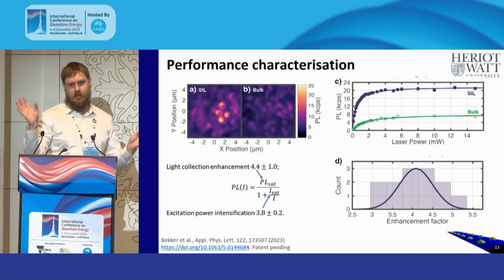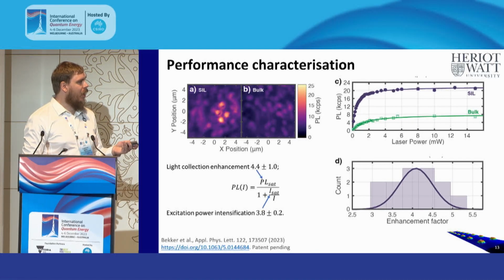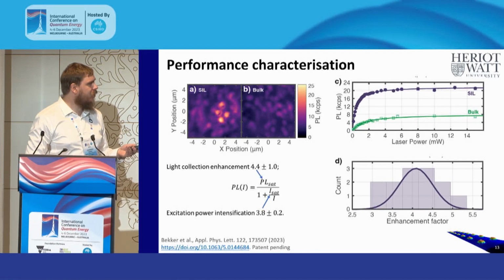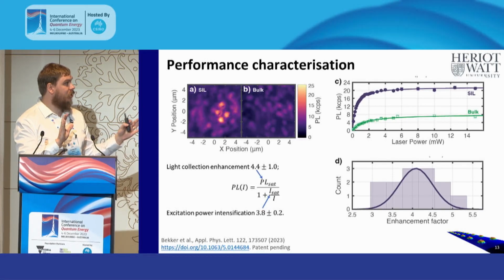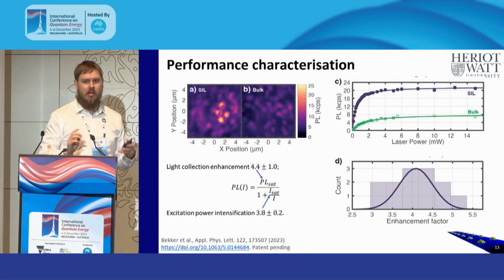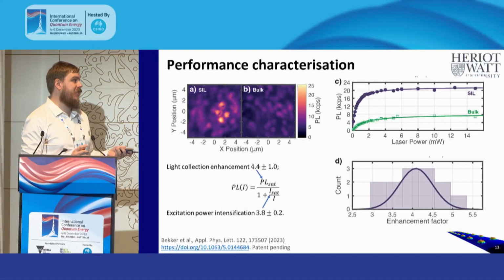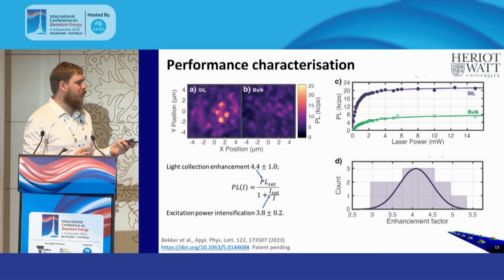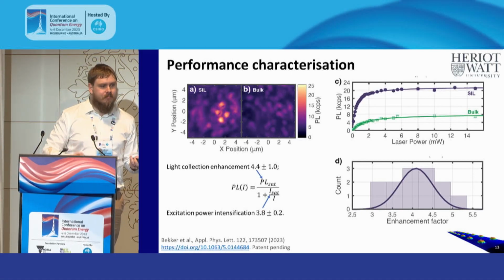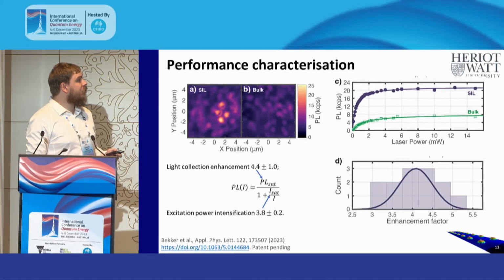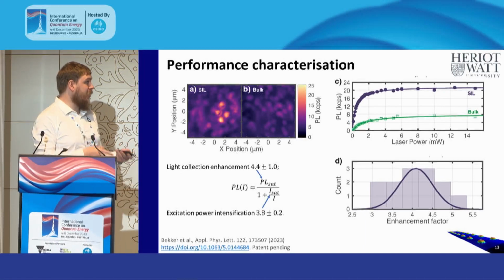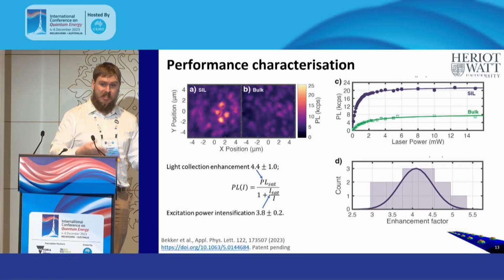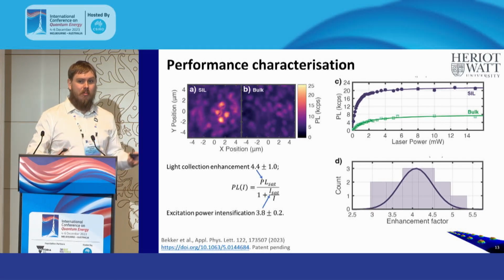And so we did statistics and looked at several of these, about 40, I think, in total between the solid immersion lenses and the bulk, and we could compare how much brighter they are. We've got about a factor of 4 at the moment in enhancement. That was very exciting for us, that we've made our first steps towards trying to make our devices as bright as we can.